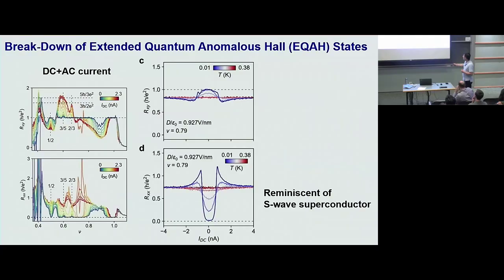But when you ramp up the current, you see some behavior that really reminds you of an s-wave superconductor, if you only look at Rxx. There's a critical current that gives you a pair of peaks in differential resistance. At the same time, the quantization of Rxy will no longer be at the integer value. It recovers what the quantum Hall liquid does. Okay?